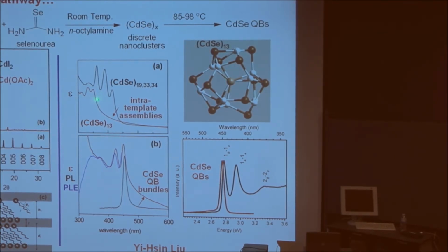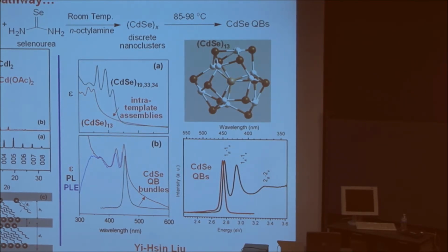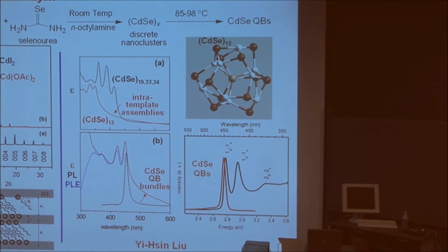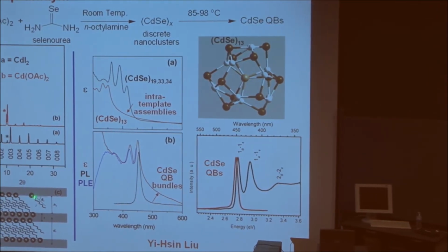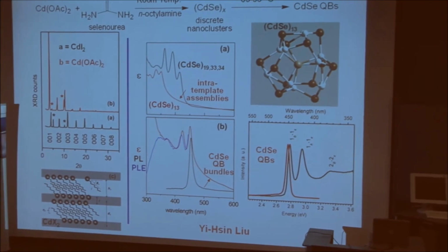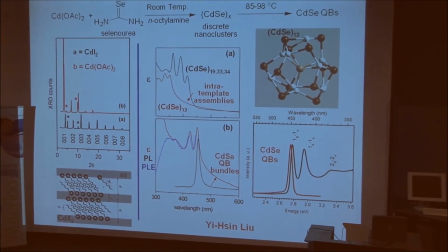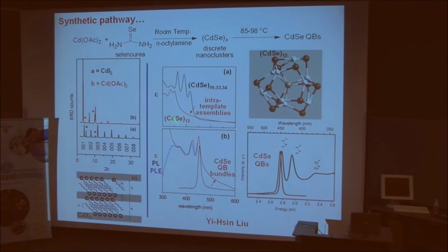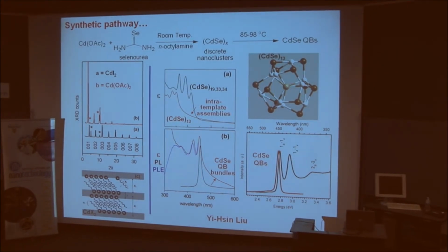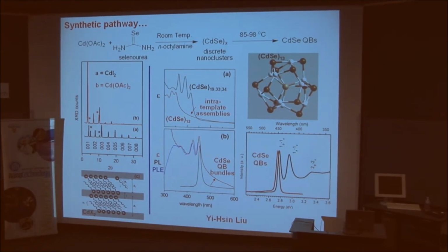You'll also notice that there's a very large scattering tail on this spectrum. That's because these cadmium selenide 13 nanoclusters are actually entrained within this lamellar structure, and I'll show you that with microscopy in a moment. So these clusters are not free to diffuse about in solution. They're trapped within the template, between the amine bilayers. Now, if we heat these discrete nanoclusters, they undergo a recrystallization process to give belts.